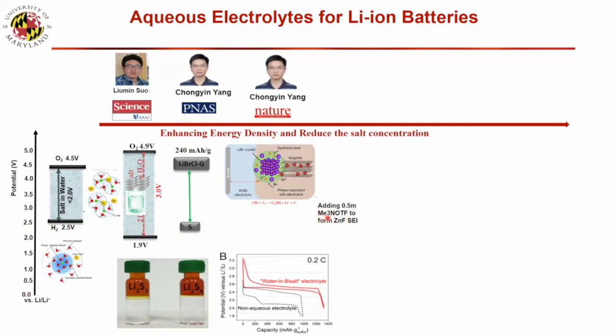And then we use ammonium OTF. We put it in as a salt. Take zinc as an example. We use zinc OTF and put in ammonium OTF. The ammonium cation is large in size, and it absorbs on the zinc surface. Then one, it can block the water, and second, it has the opportunity to reduce. So it can form a zinc fluoride SEI. Is that the same as in a lithium metal battery? If you have zinc fluoride with a high interface energy, zinc is not easy to penetrate and form dendrites. So we can get a really high Coulombic efficiency. We will show some data.